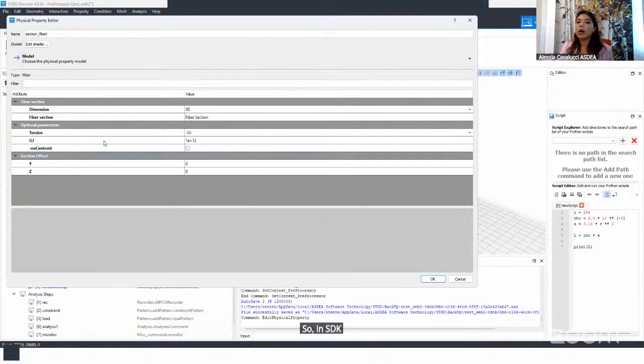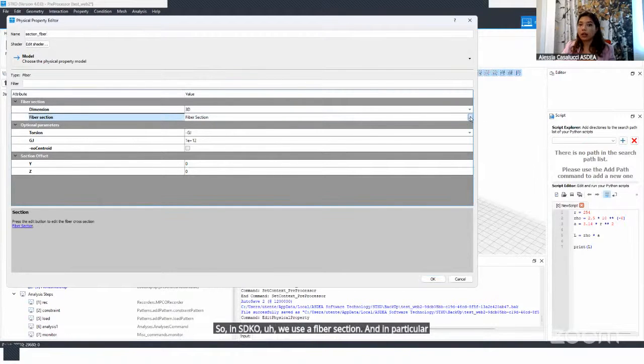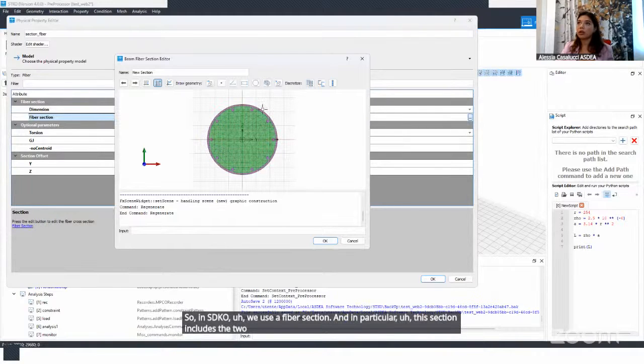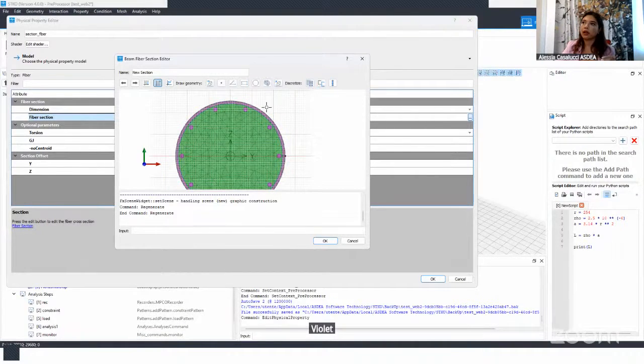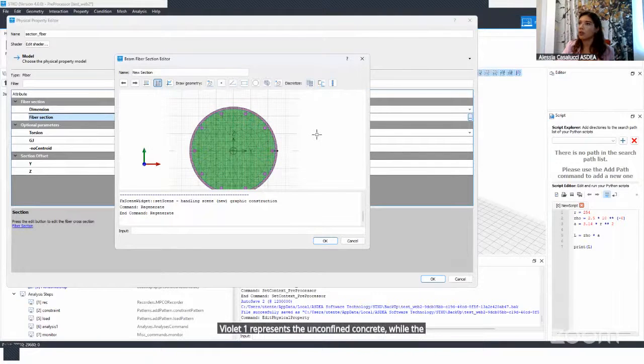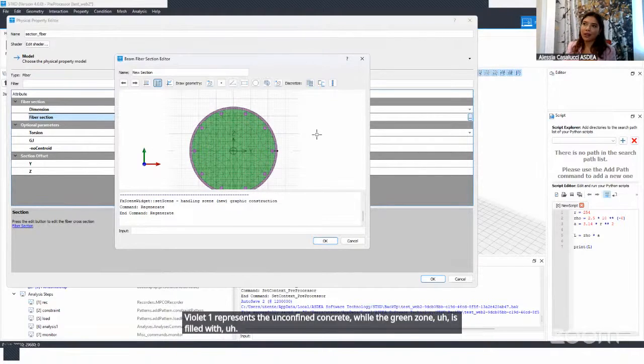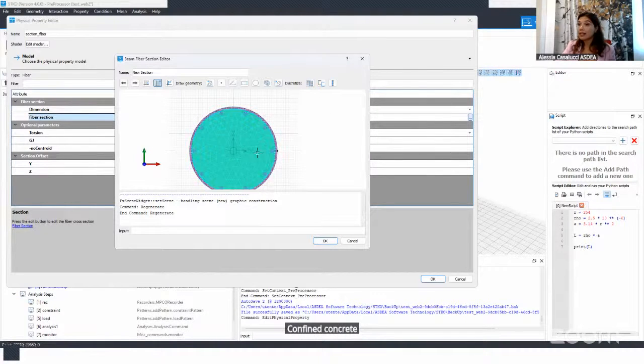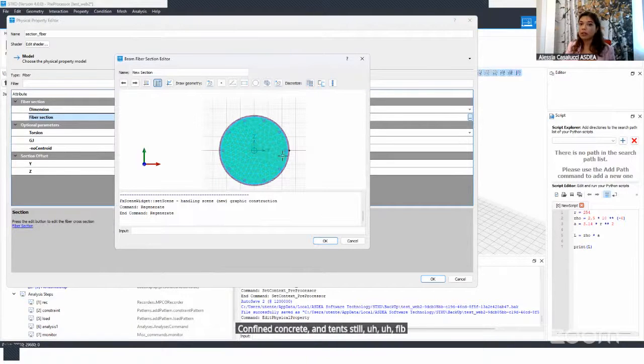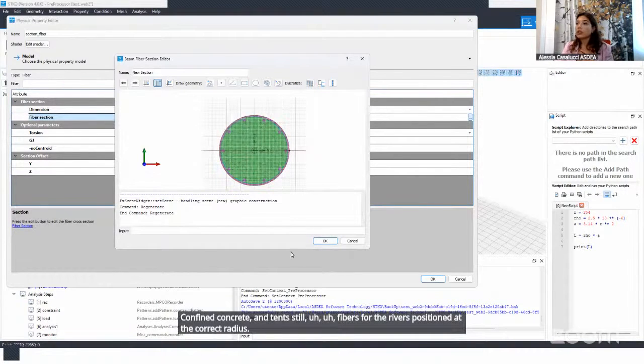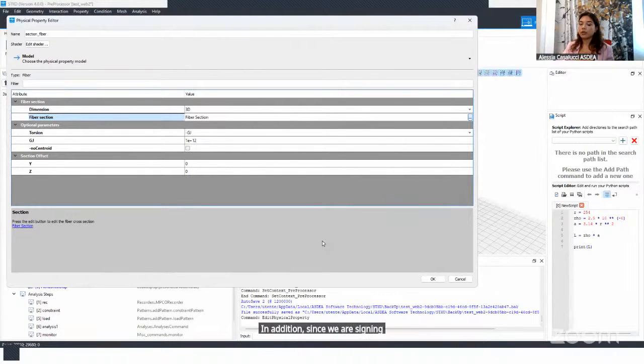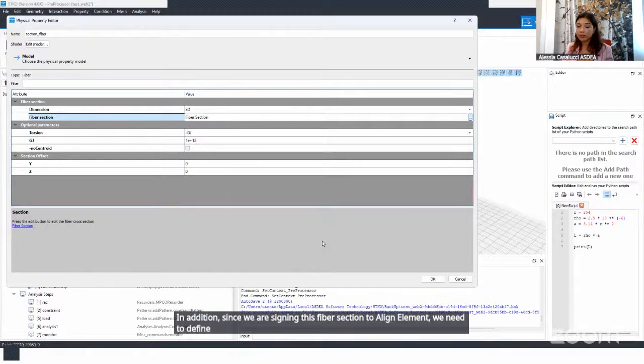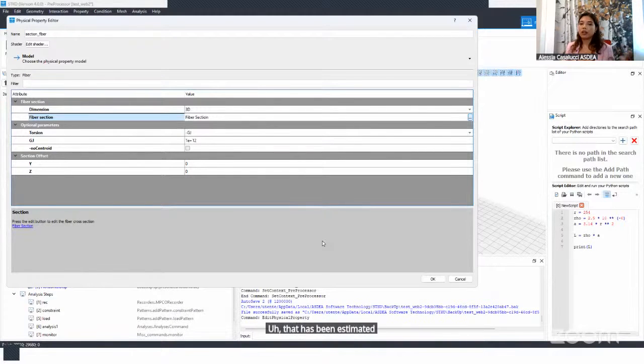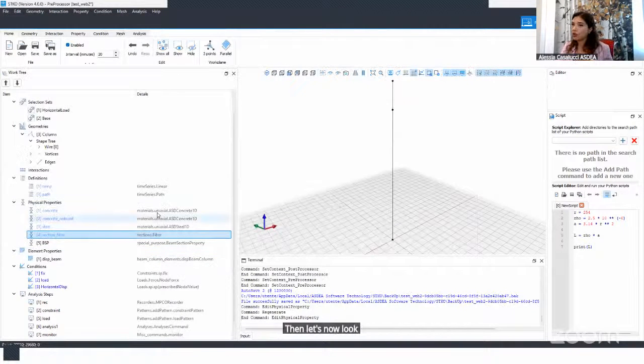So in STKO, we use a fiber section. In particular, the section includes the two concrete zones. The violet one represents the unconfined concrete, while the green zone is filled with confined concrete, and 10 steel fibers for the rebars positioned at the correct radius. In addition, since we are assigning this fiber section to a line element, we need to define a torsional rigidity that has been estimated from physical and geometrical data from the test. Then let's now look at the concrete material.